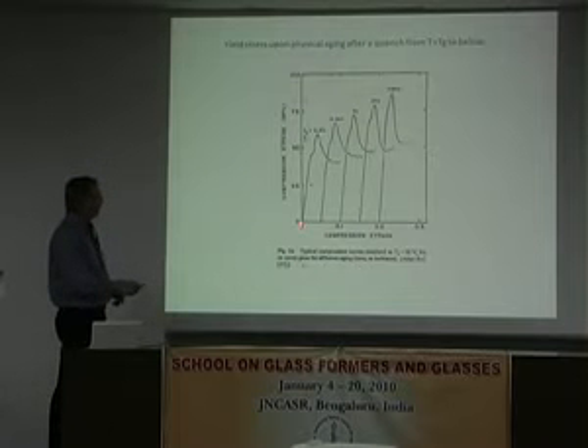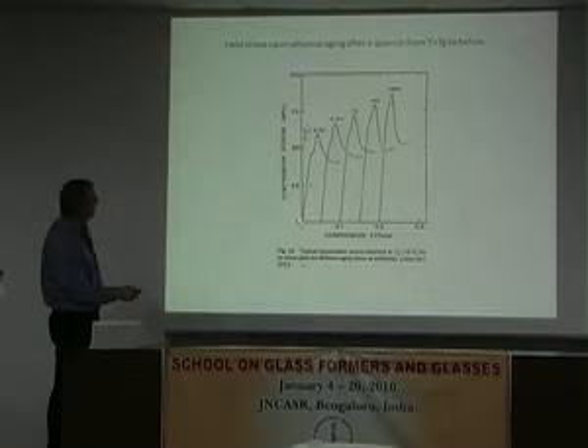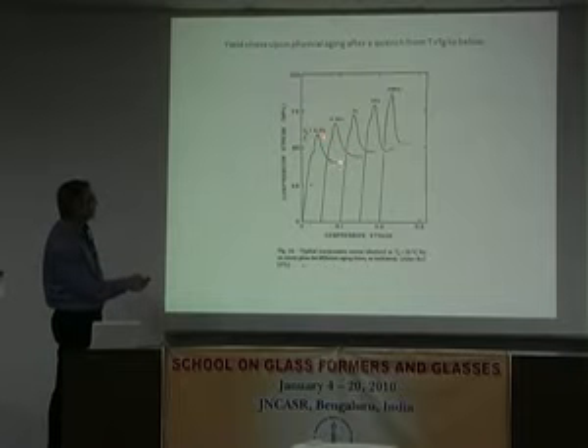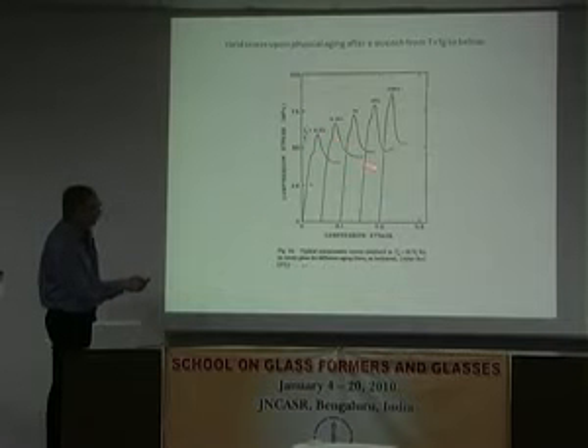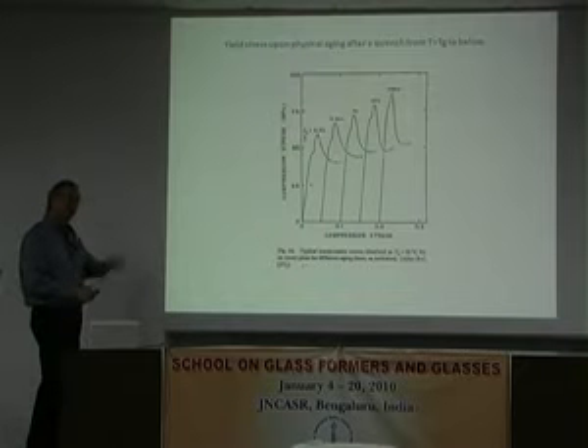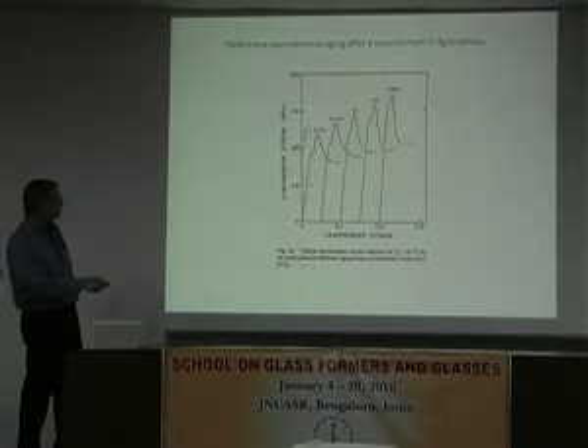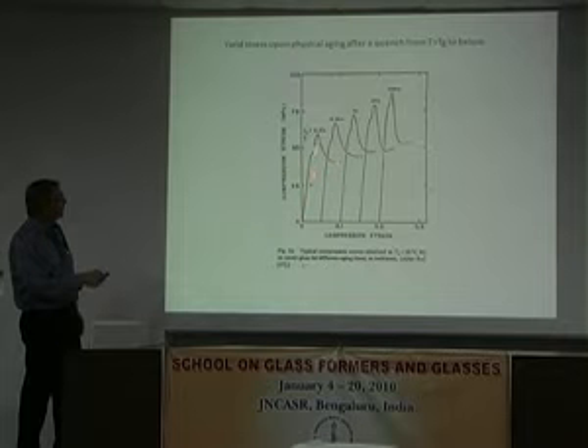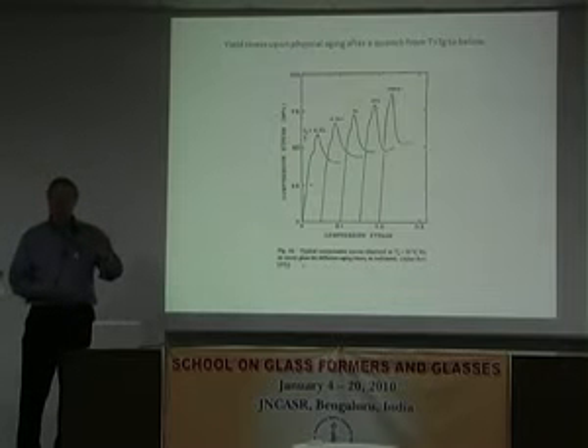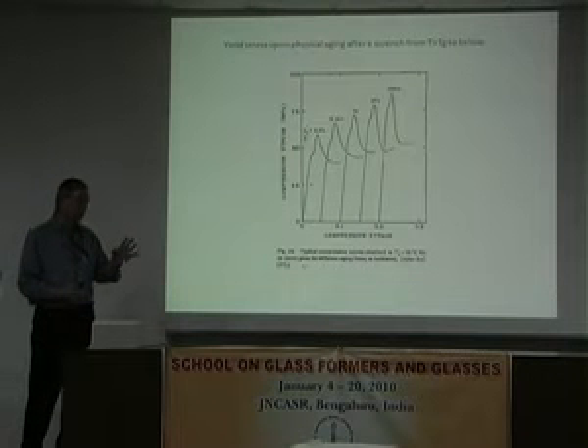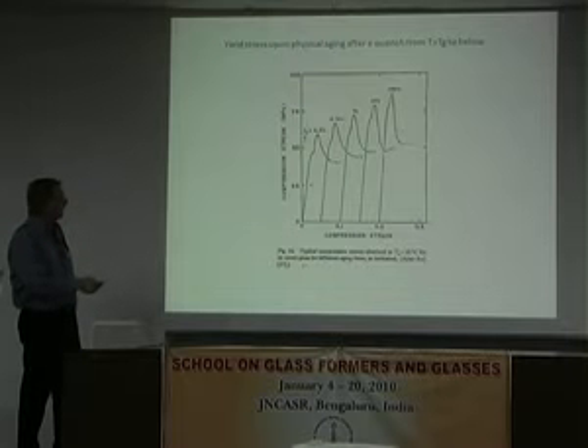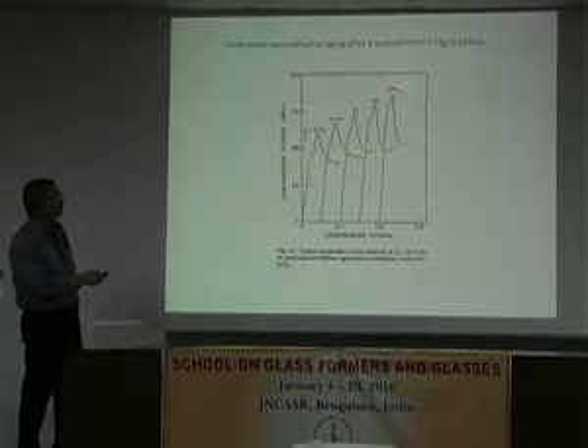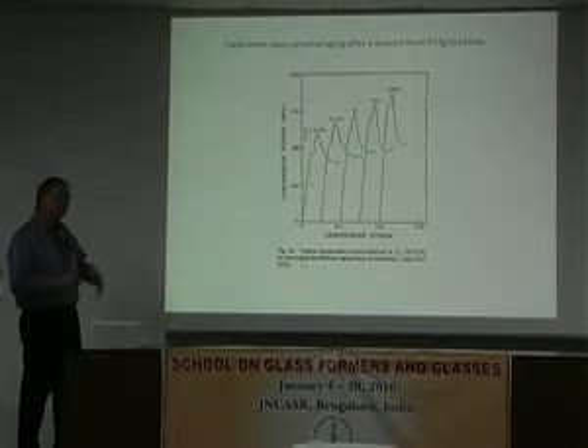If I run up directly, it does the same thing. But here's yield. It goes up, goes to a maximum, and then comes down. And some materials will go up. Some materials will continue to go down, depending on the material, if it strain hardens or strain softens. But in this case, the yield was associated with some shear banding. Okay, so it's an instability. And we were interested in knowing how this ages, so you can see it ages. And we were interested in that.